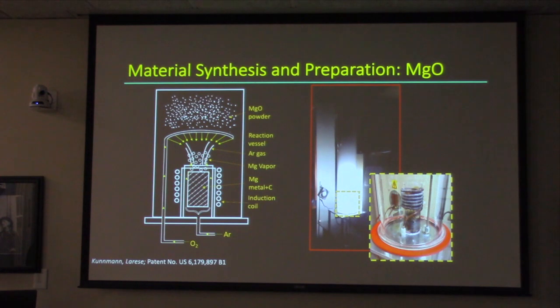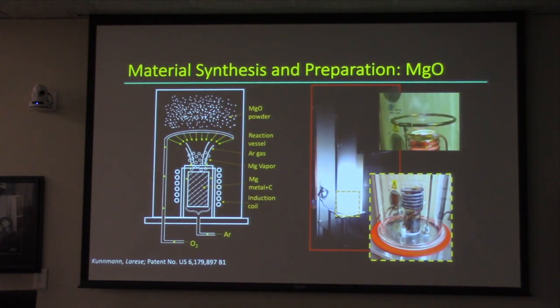And I guess the apparatus looks like this, and it looks like a lighthouse when it's working because it's a high temperature process. And amazingly, it works well enough to give you really narrow selectivity. So we were happy about that. And sometimes being lucky is way better than smart. And so here's an example of how this reaction begins. There's a halo. We can introduce gases here, and we can start off with metallic compounds that allow us to introduce another material as a dopant. So that's the way it goes. If you care, you can look up the patent.